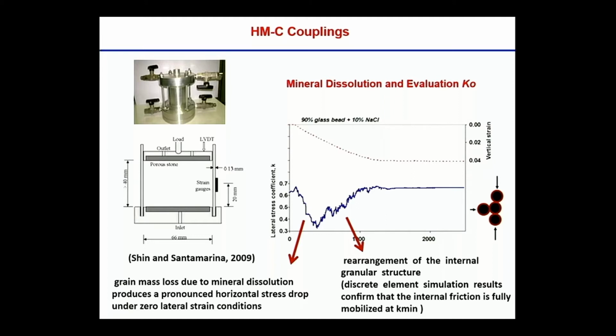So what happens when we dissolve this mineral, part of the solid phase, is that we have a volumetric strain, a shrinkage of the sample, but also the lateral stress decreases due to the grain mass loss due to mineral dissolution. But at a certain point it increases due to the rearrangement of internal granular structures. So you have some dilation that is related to an inelastic response of this material, that we are trying to model as well in a few moments.